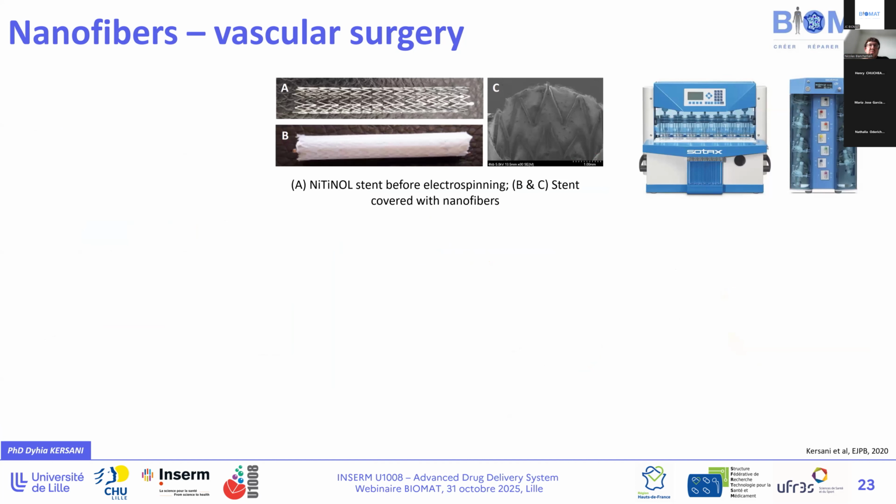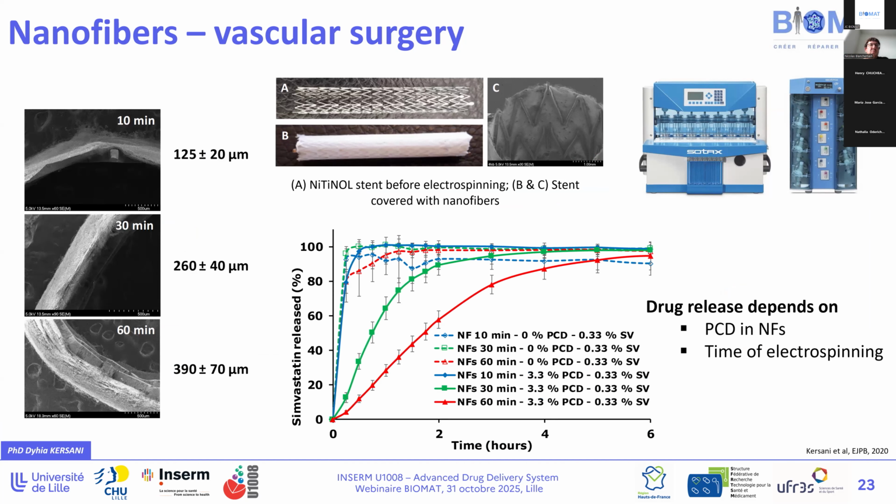So we succeeded in coating the stent with an electrospun membrane, and we can control the thickness of the membrane with the time of electrospinning. We can multiply the thickness of the membrane by 3 when the time is increased by 6. We also evaluate the drug release.